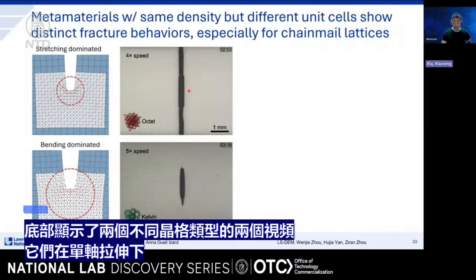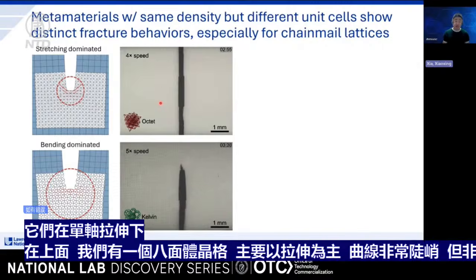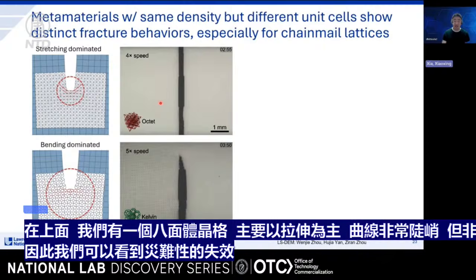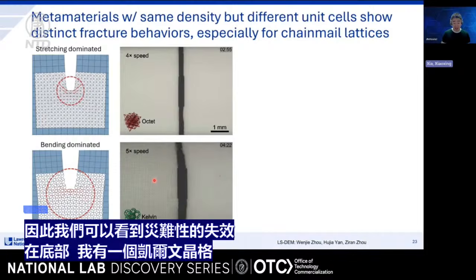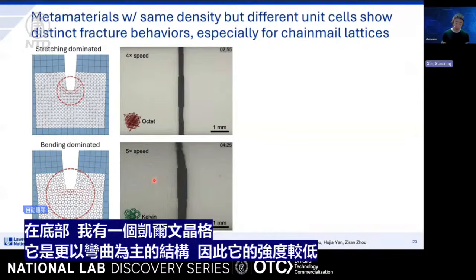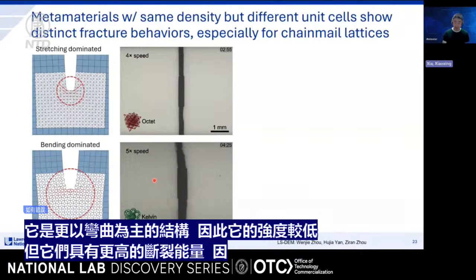On the top, we have an octet lattice that is really stretching dominated. It's very stiff, but it's very brittle. And so we can see a catastrophic failure. In the bottom, I have a Kelvin lattice. It's a more bending dominated architecture. So it has a lower modulus, but it has higher fracture energy. So it's tougher. It takes more energy to propagate that crack as we stretch the sample.